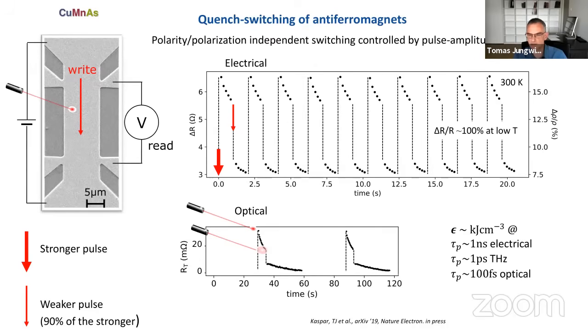Right. So, quickly remind me, the first question was about the relaxation. We think that this type of switching is quite unique. We could not find any counterpart in the ferromagnetic literature. For some reason, we get stability, or long-term metastability if you want, of these very small domains. From the microscopy measurements, we can infer that these features are on the scale of 10 nanometers or maybe even smaller. Now the question is what keeps these features stable or metastable for macroscopic timescales.